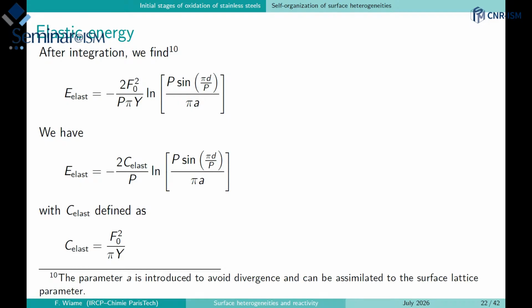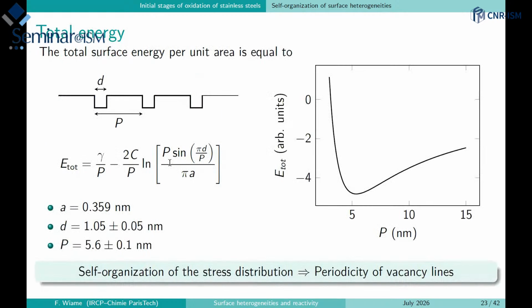And if we want to calculate the total energy, then we also need to take into account the fact that to create a vacancy we need to break some bonds, so it costs some energy. And so the total energy will be, in fact, the energy needed to create this bond per unit area. So this is linear energy. And here, this is the energy that is gained, let's say, by the reduction of the elastic energy. If we draw this, you can see that we have a potential like this, where we have a minimum value, which in our case corresponds to 5.6 nanometers, with a distance d, which is, as we have said, 3 times the lattice parameter. And so we can understand that it should be periodic.